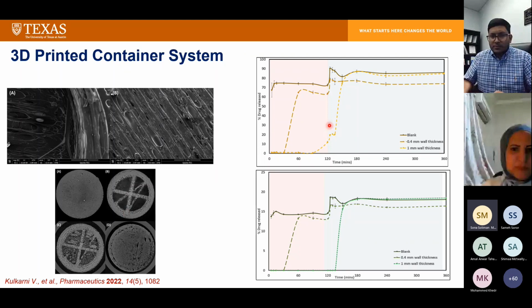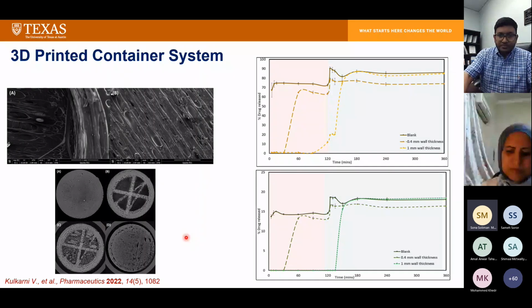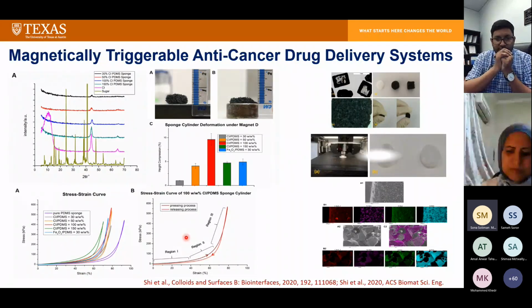And this is basically to show the release pattern of the drug. What we found that by simply controlling the wall thickness and the container composition, we could easily delay or control the release. So that may be an ideal paradigm for biologics formulation or unstable formulations in the future. We have just published this paper last week. So this is another example.